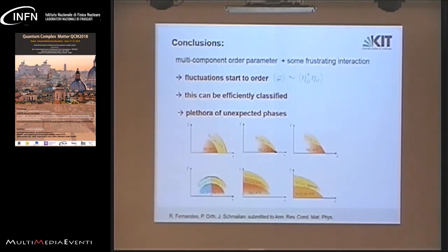What he finds is a cusp, a very sharp structure, very much in agreement with the fluctuation seen in the Raman spectrum. There's only one interpretation to my mind. That means it's something else but the lattice that is going on. So we are saying if I were artificially to keep the lattice constant and fixed in place, there would still be a phase transition. I never thought that this was doable in experiment, but Ian Fisher showed that it actually is.